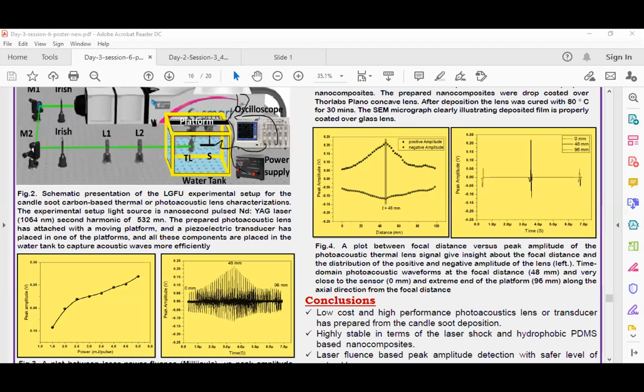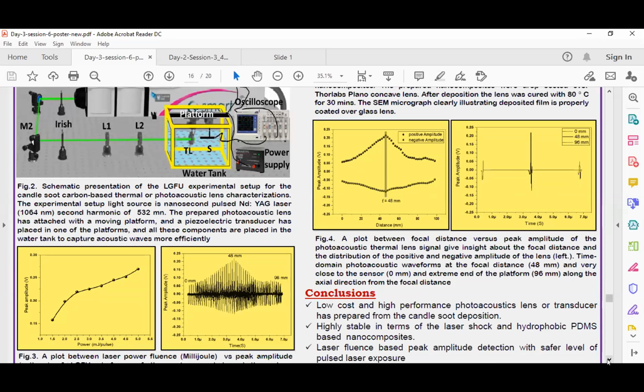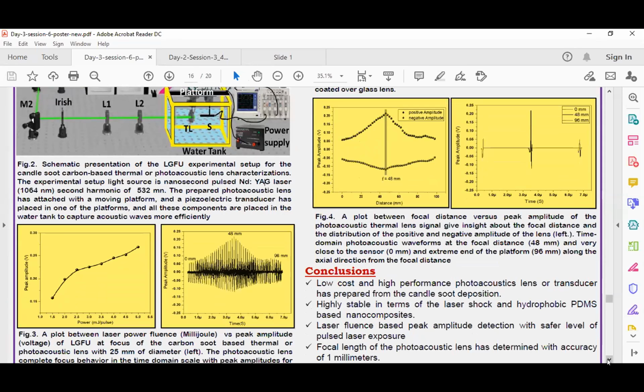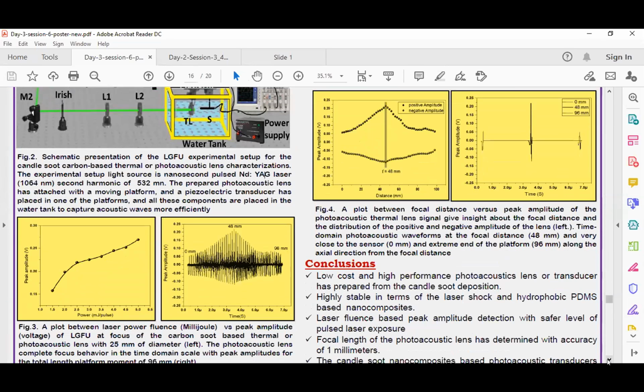It is a photoacoustic lens. I also checked the power versus peak amplitude. I used 1 to 5 millijoules per pulse, and beyond that it is very hard to pump the lens because it is going to break due to the high energy. The left figure shows the pump energy versus peak amplitude, and the right figure shows the photoacoustic characteristics of the lens, particularly the one developed with the carbon nanocomposites.